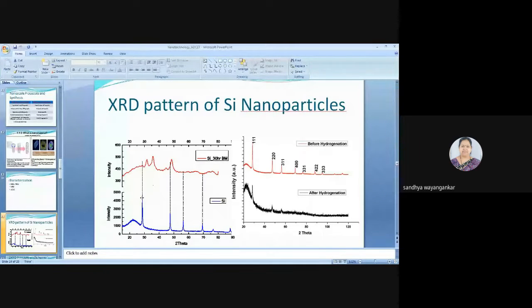But what happens when you break a crystal? The crystallinity is lost. The fine crystals are not remaining there, and the material becomes a more amorphous kind of material. There are irregularities in the material, and you can see the peaks have got disturbed now. There are no sharp peaks, but there are peaks, so it is not complete. The basic material is crystalline, but it has not lost all its crystallinity, it is reduced.